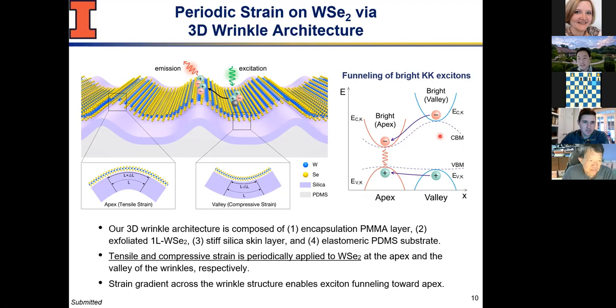It's interesting, where if you are an exciton, so if you're an electron hole pair sitting on a valley, sitting on this point, they might see an opportunity to try to go uphill, geometrically speaking, and then try to gather around the apex because the energy there is just lower. So it gives them an opportunity to get to a lower energy state.